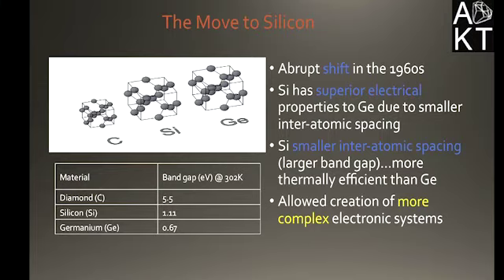And so silicon actually has superior electrical capability because it has smaller interatomic spacing. The group 4 elements, carbon, silicon, and germanium, all crystallize in what's called the diamond lattice structure. And germanium, the atoms of germanium are actually a little bit further spaced than they are in silicon. And what that allows in silicon is that the properties can actually become more thermally efficient than germanium because it requires more energy to excite these electrons away from their valence state.